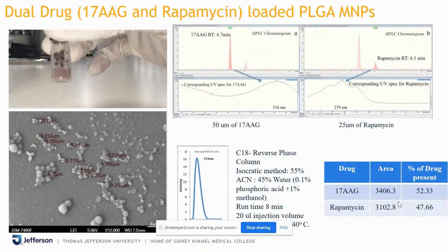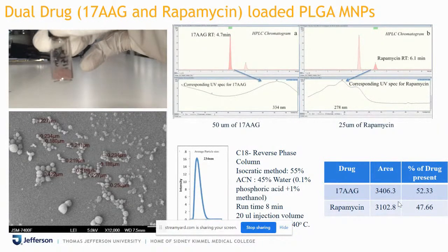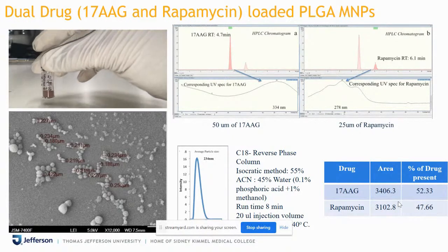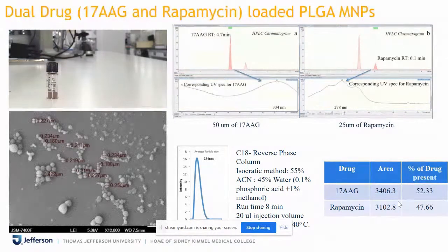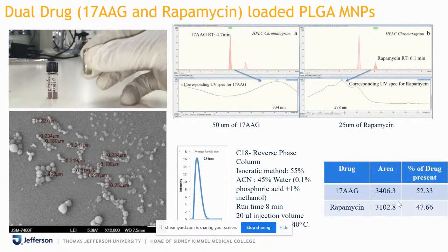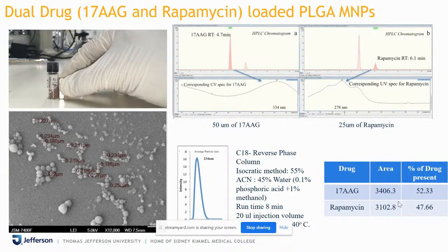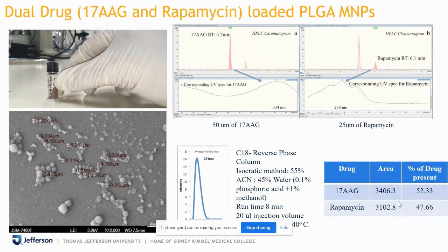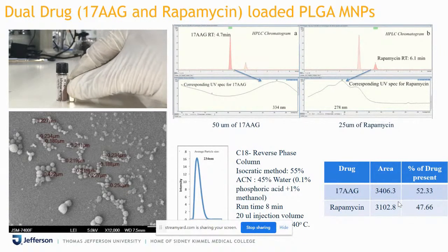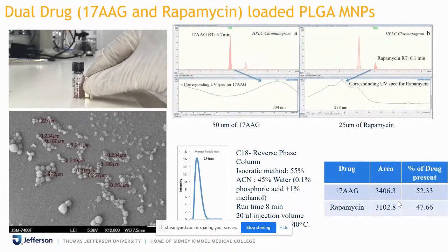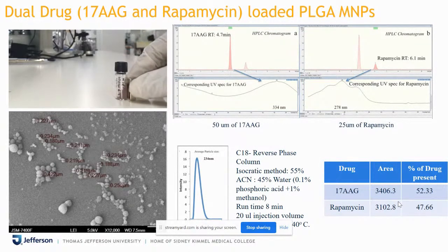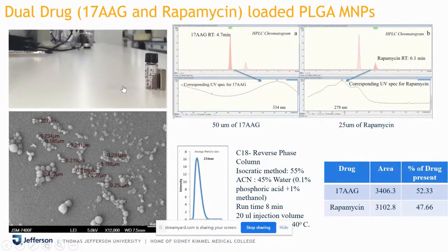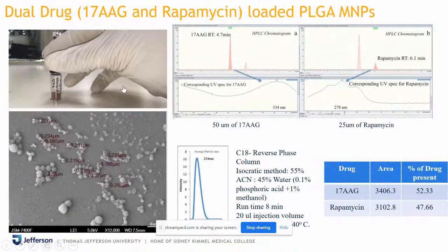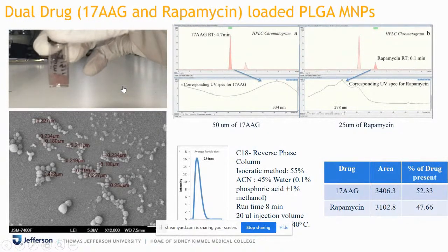So, having some experience with drug delivery using PLGA-based systems, we went ahead. As I told you, we developed rapamycin, which is an mTOR inhibitor, along with 17-AAG in PLGA-loaded MNPs. So it's a dual drug-loaded PLGA MNP system. You can see in the video that I created the nanoparticle powder, which was lyophilized, and it's at room temperature right now.